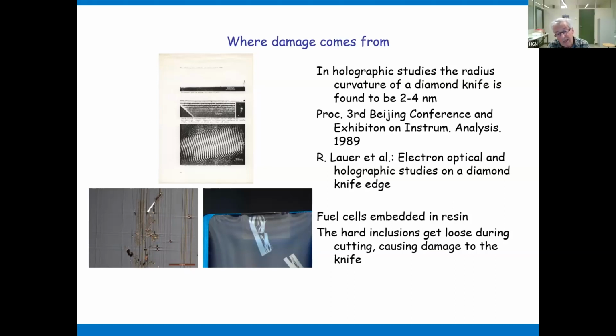Now, all the sample testing I'm doing are done on new knives. So when you see these lines in a vertical direction, this is all the damage from one single sample or from one section or a few sections. The knife marks cannot be seen directly on a cutting edge in the optical microscope. I then cut sections again, maybe an empty resin block, and then in the image on the right side, you see the sections cut at maybe 50 nanometers, they split, and this shows you the condition of the knife.